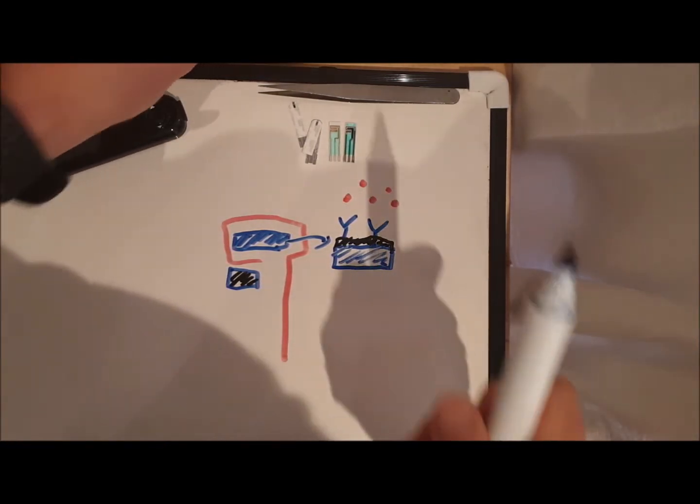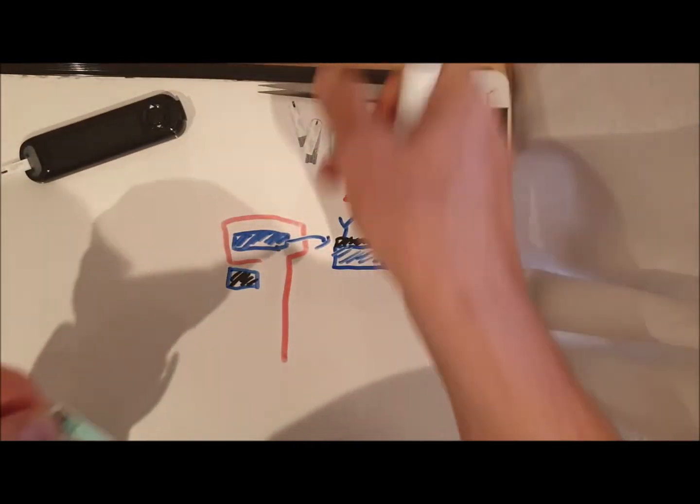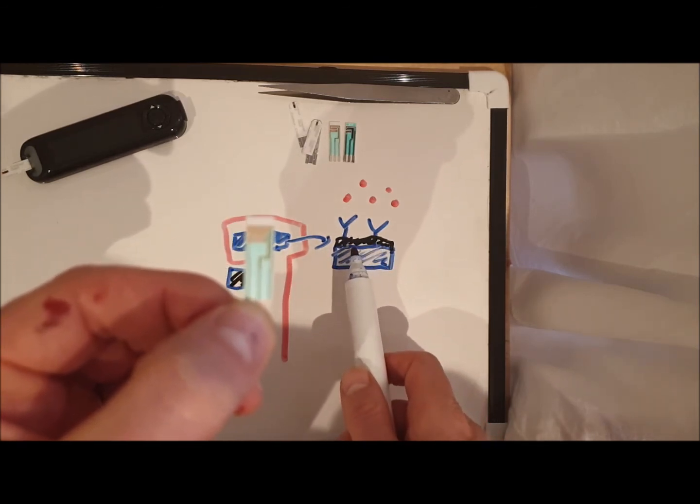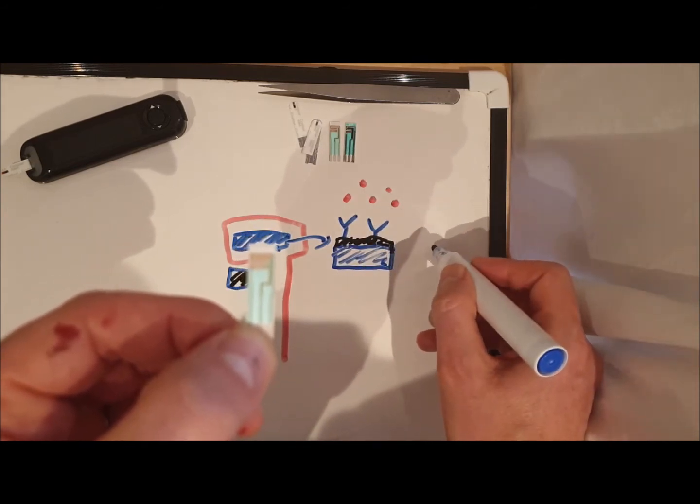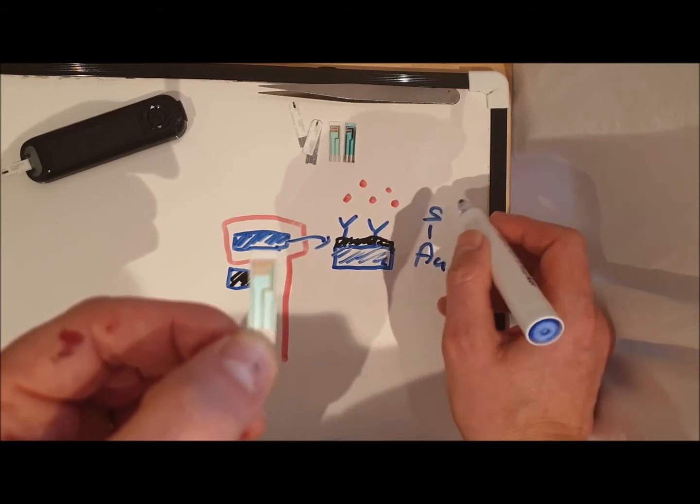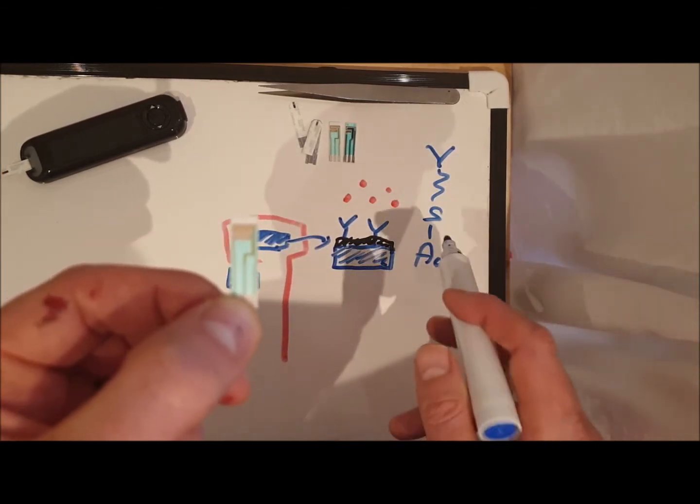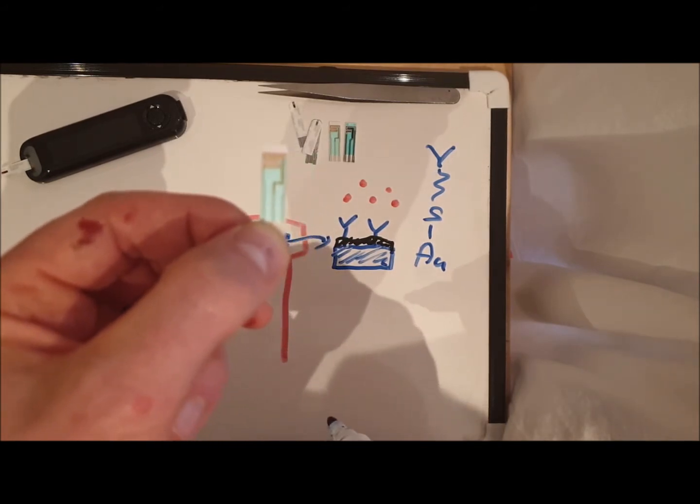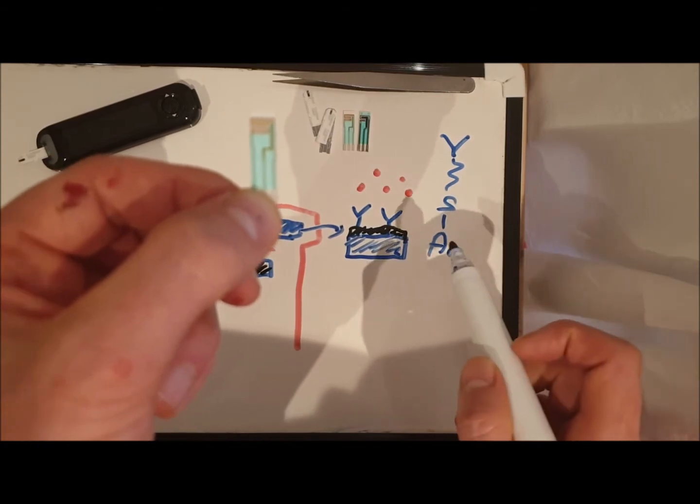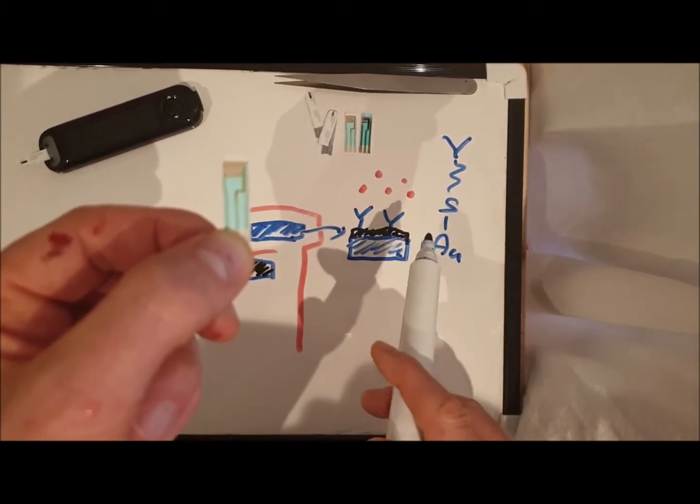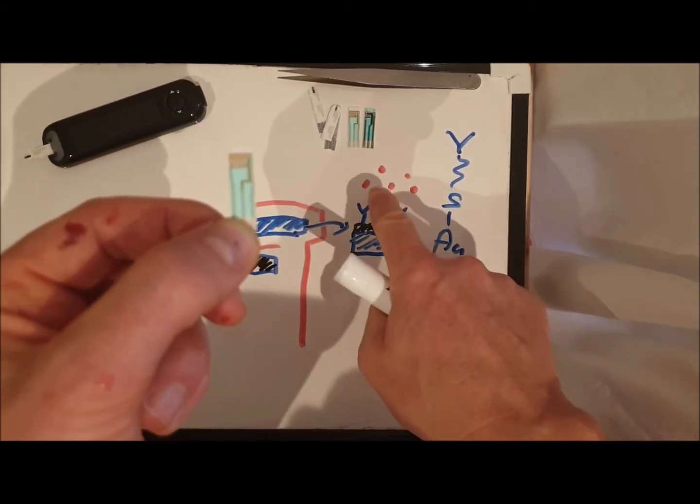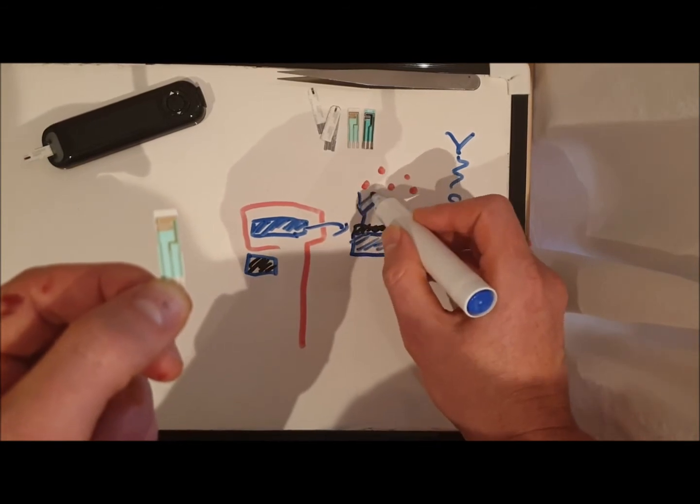In some ways, that's the sensor made. Take one of these gold screen printed electrodes. We would want you to functionalize the surface with your antibody. If you asked how to do that, we would tell you about the gold surface and forming a thiol layer. Then to the thiol layer we could couple your antibody to the other end of the thiol. This is called SAM chemistry—self-assembled monolayer. It's really well documented, it's decades old, and it's fairly robust. It kind of works quite often. We would teach you about putting down the antibody, putting down maybe a blocking layer to stop what's called non-specific binding, and maybe how to put down the reporting molecules.